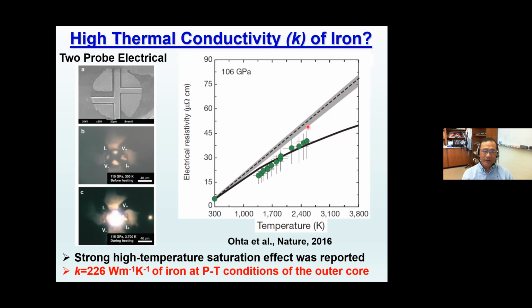So if you now use that value and the Wiedemann-Franz law, you get a thermal conductivity that is about 200 watts per meter per Kelvin, basically extremely high. And so then you run into the issue that the Earth's inner core is really young, and in early Earth you don't have a compositional energy source to power the geodynamo and such.